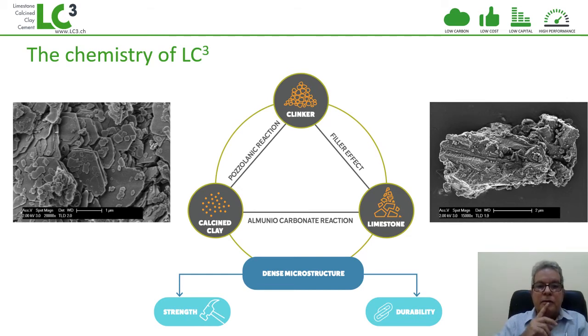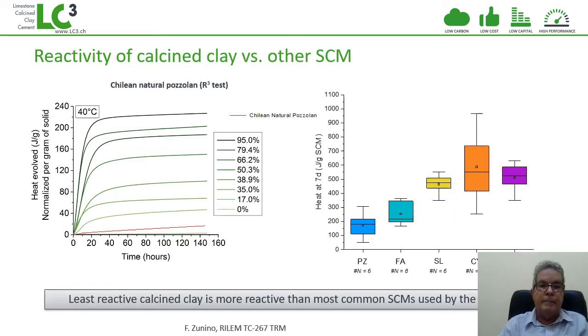But the most important thing is that between the alumina that is present in the calcined clay and the carbonates from the limestone, there is a synergy that enables the formation of an AFm phase, which is called carboaluminate. And this phase is also contributing to strength, contributing to a denser microstructure, and at the same time is contributing to durability. And this is the magic of the LC3, to put it in a way.